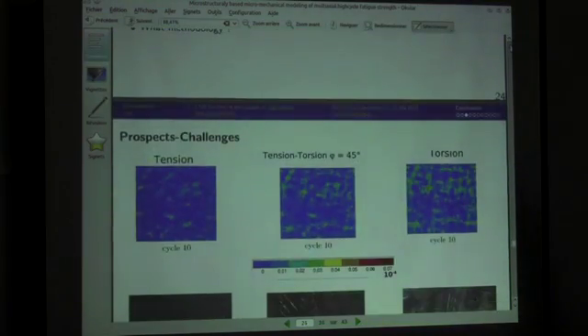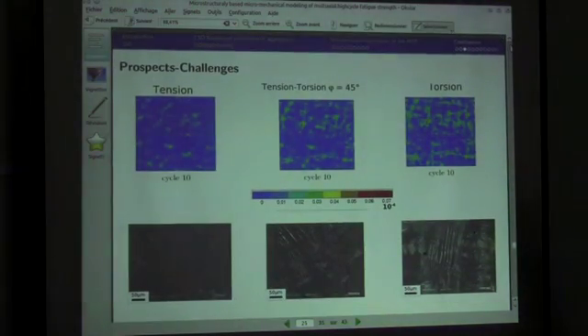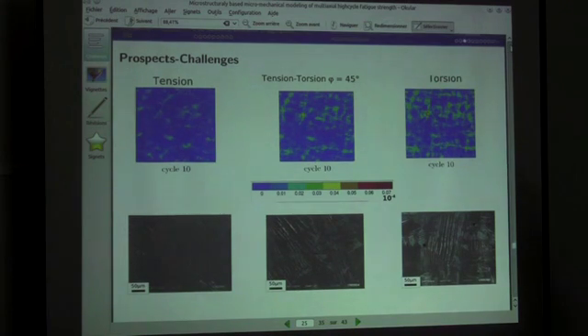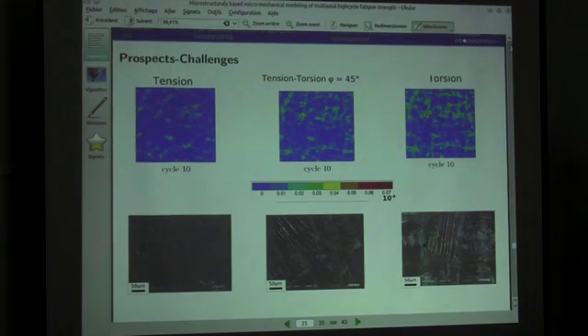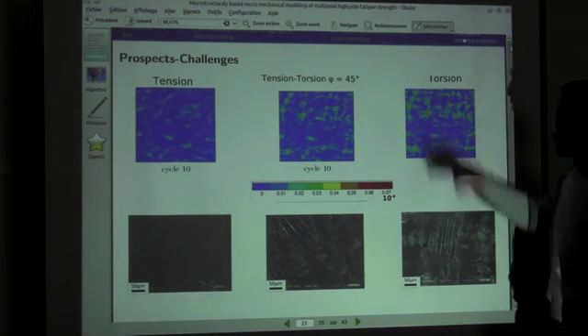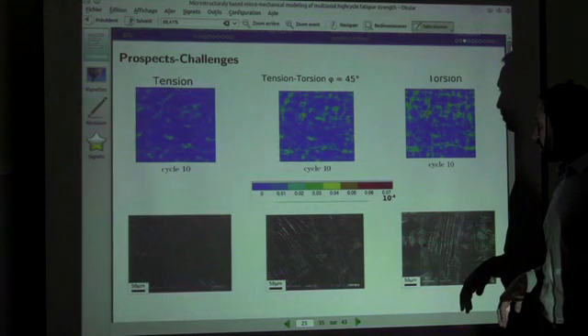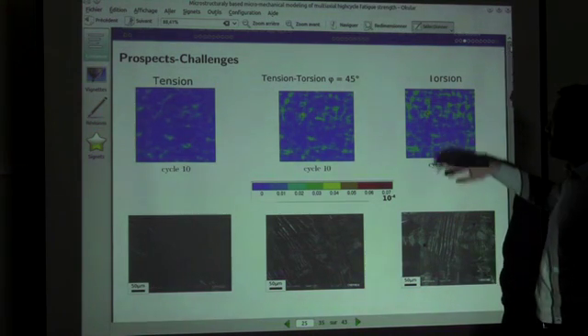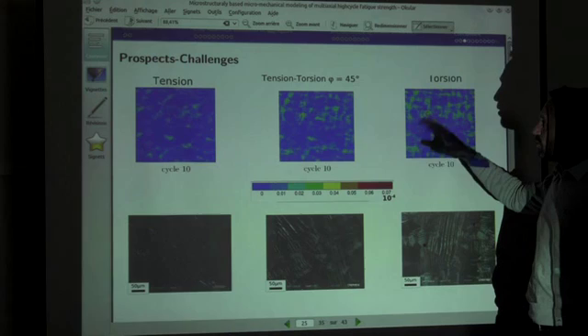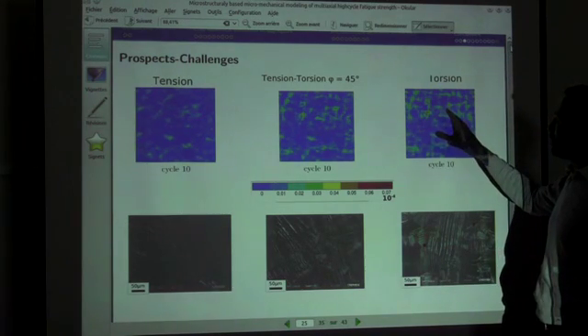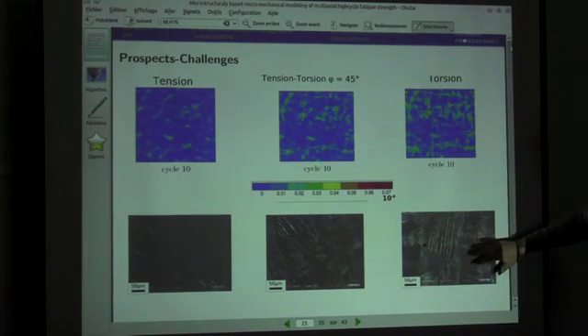So what is the best methodology? We tried to secure our computations by comparing experimental and numerical results. So we did the same experiments as we compute, in terms of loading cases, and you can see that when you look at the plasticity developing between the different loading cases and you compare to the experimental observations, in terms of intensity of slip, you have some similarities. But it's very hard then to compare directly, to quantify the data.